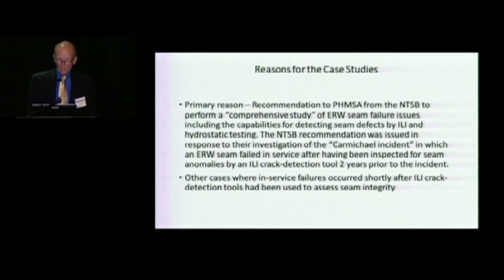Now, how did we get into this study? The reason for the study was the accident that happened at Carmichael, Mississippi. After the NTSB investigation, a recommendation was made to PHMSA to perform a comprehensive study of ERW pipe seam failure issues and to look at, among other things, the capabilities for inline inspection and hydrostatic testing. This part of it was the inline inspection part. We also recognized, at the same time as the Carmichael incident, that there were other cases where significant cracks in ERW pipes had not been found by inline inspection. So that was the driving force for the study.